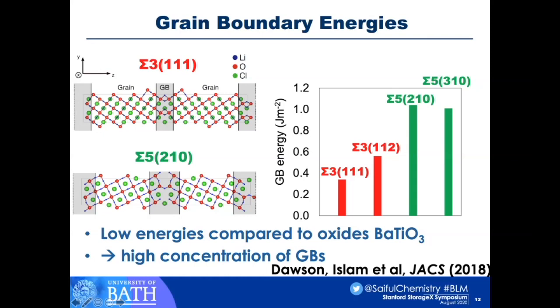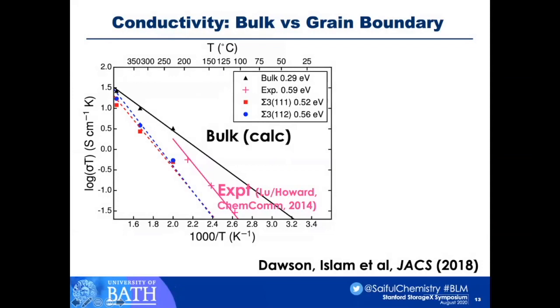So the next question is, how do they affect the conductivity? We performed very long time scale potentials-based molecular dynamics, from which we can derive diffusion coefficients, and then convert them to conductivities. So let's look at the Arrhenius plot, the classic log sigma T against 1 over T. The pink line is the experimental data from Howard's group, and the black line is our calculated bulk value, which we've extrapolated down to lower temperatures. The dotted lines are the sigma 3 conductivities from the grain boundaries, which we've extracted.